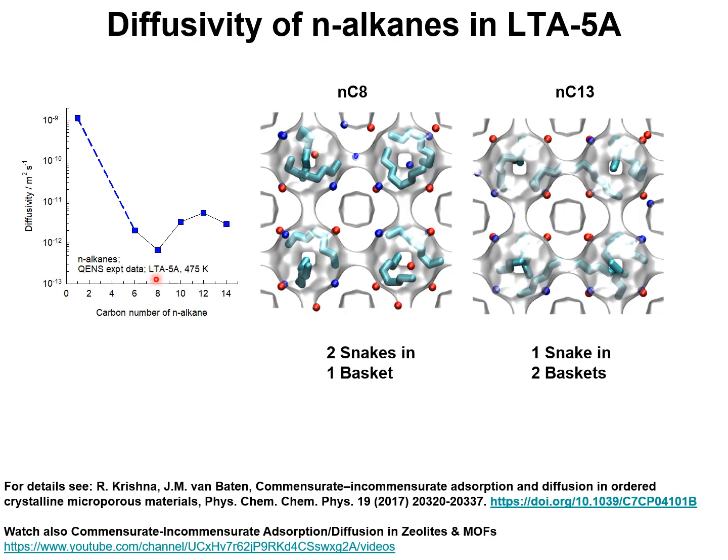The diffusivity for normal octane NC8 is lower than the diffusivity of tridecane, NC13. To understand the minimum here for NC8, let's look at the computational snapshots showing the conformations of NC8 and NC13 within the cage window structures of LTA5A zeolite.